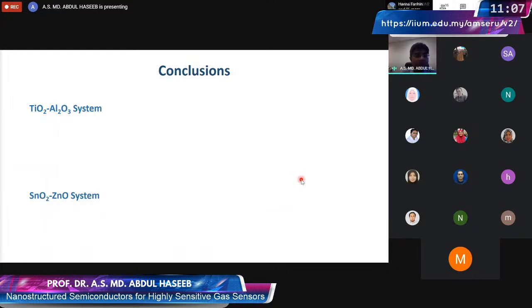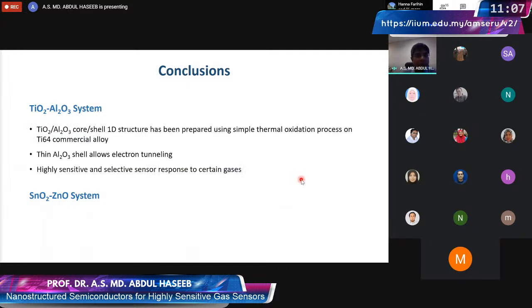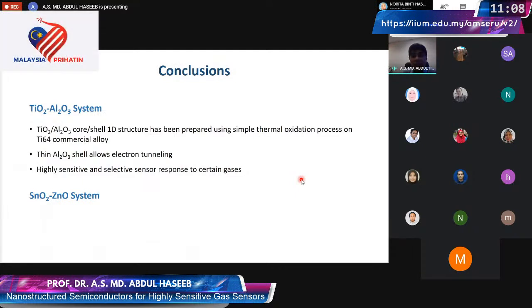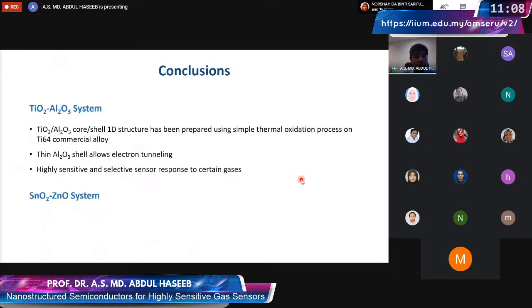And then what we did is share our experience with 2 material systems, and we have found out that we can grow this nice, well-structured, good enough morphology of mixed oxide in 1D form by a simple thermal oxidation process. We need to control certain parameters, and the process doesn't involve highly sophisticated equipment or highly costly chemicals. And we found that we have a thin layer on the top of the titanium core, and in spite of the fact that aluminum is an insulator in bulk form, this thin layer allows electron tunneling, and hence allows the sensing to be possible in this particular system. And we get a highly sensitive and selective sensor for certain gases.